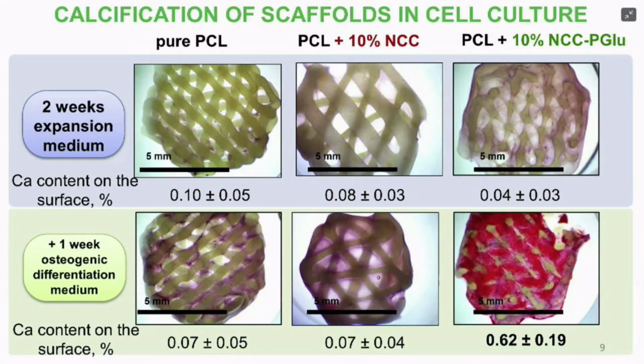We established that after cultivation of human mesenchymal stem cells in growth medium, only traces of calcium were detected in all kinds of tested scaffolds, here are the values, percentages. The same situation was observed after the osteodifferentiation of these cells in scaffolds made of pure polycaprolactone and polycaprolactone with unmodified cellulose. However, evident calcium deposits after the osteodifferentiation of MSCs were detected for the polycaprolactone scaffold containing polyglutamic acid modified cellulose. In this case, the better deposition of calcium salts is explained by improved capturing of calcium ions by carboxylic groups of polyglutamic acid, which is bound to the nanocrystalline cellulose incorporated in these materials.